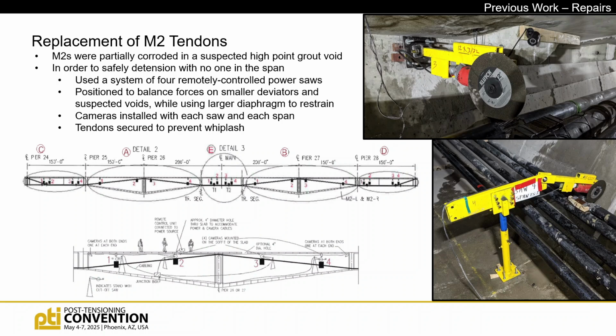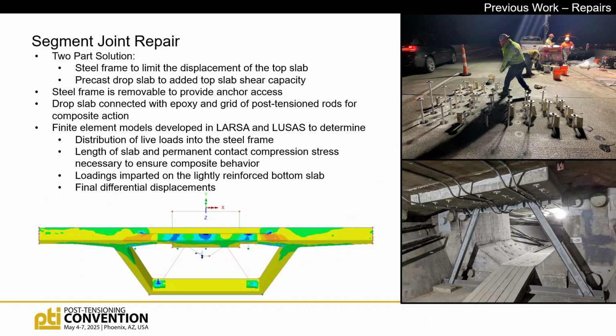diaphragms. But in this case here, we had a tendon that we knew was corroded in a high point, very large void, and we didn't really want people right there next to it doing this sort of work. We were looking for a safer way to do it. So working with Freyssinet, we came up with a method using a system of 4 remotely controlled power saws that were strategically located to, again, balance those forces on either side of the smaller deviators and then use the larger diaphragms to handle the out-of-balance forces. So nobody had to be in the bridge, or at least in those spans, at the time that we were doing that.